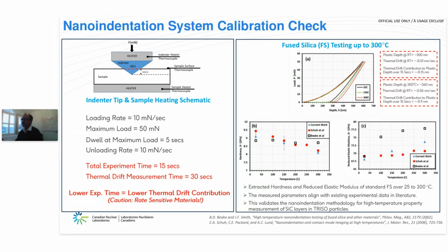The plastic depth at room temperature was around 300 nanometers, and the thermal drift that we measured for room temperature measurements was on the order of minus 0.01 nanometers per second. This is the best we can achieve within our lab itself. But when we consider this negative 0.01 nanometer per second as thermal drift, and the total duration of the experiment, which is 15 seconds, the drift contribution in our total displacement data was quite small, 0.15 nanometers, where the plastic depth was around 300 nanometers.